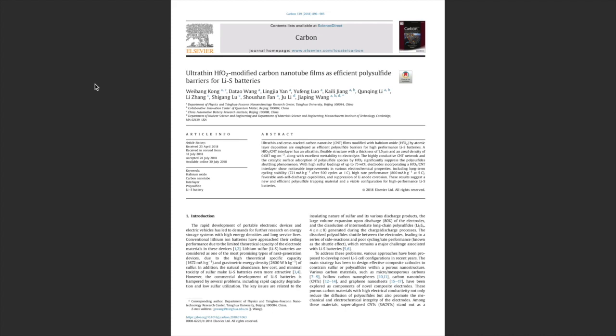Long-chain polysulfides generated during the charge and discharge processes dissolve and shuttle between the electrodes, leading to side reactions and poor cycling performance. In this paper, ultra-thin hafnium oxide modified cross-stacked carbon nanotube interlayers are introduced to trap polysulfide and prevent migration to the anode. Experiments have shown improvement in long-term cycling stability, high rate performance, favorable anti-self-discharge capabilities, and suppression of lithium anode corrosion.